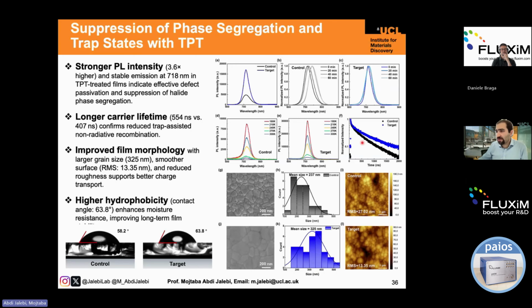And also, we observe a longer carrier lifetime for the TPT thin film. The other aspect we observe is enhanced morphology of the perovskite. I mentioned earlier that with this high bromide content, you normally have a challenge to form a good perovskite thin film. And with this triple passivation strategy, we observe a larger grain size as well, average grain size.